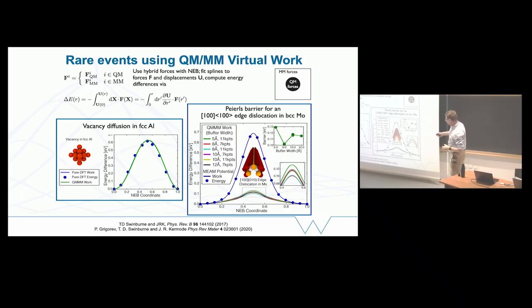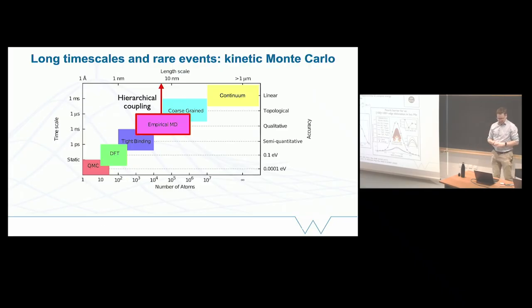And you can see they're massively different from what you get, for example, with an empirical potential in this case. So I think this is quite a good example. It shows that it can be dangerous to rely on interatomic potentials outside of the domain where they have been calibrated. And even if these calculations are expensive, it's useful to be able to do them occasionally to validate and to provide information.